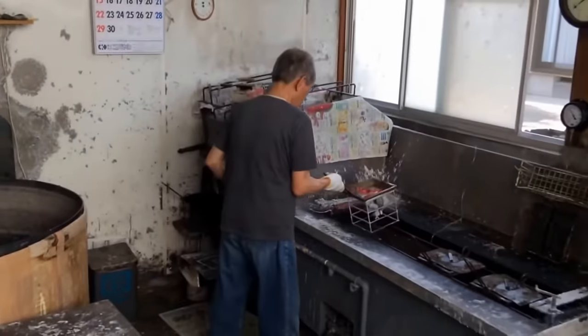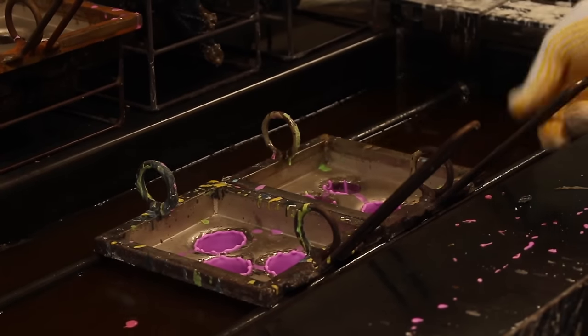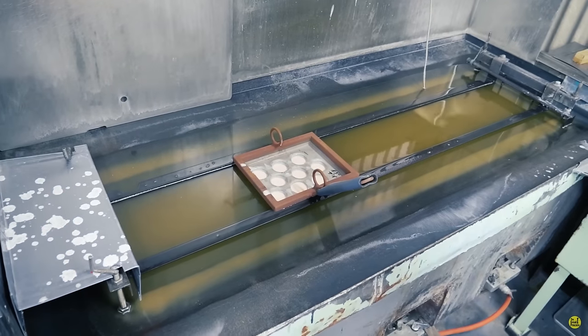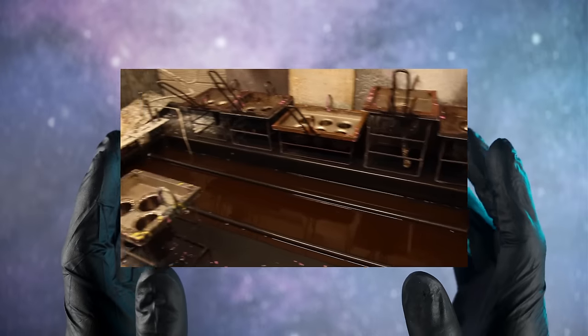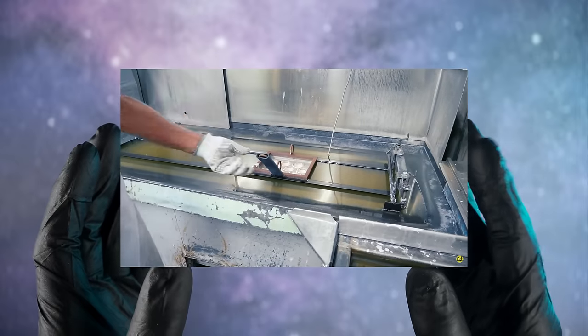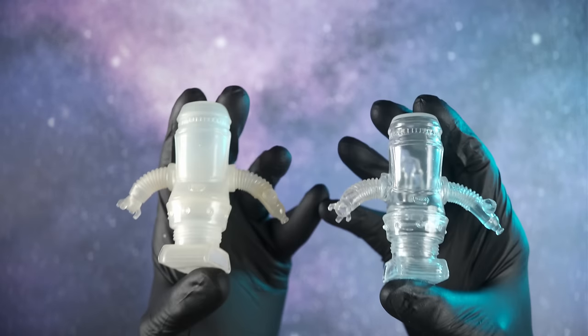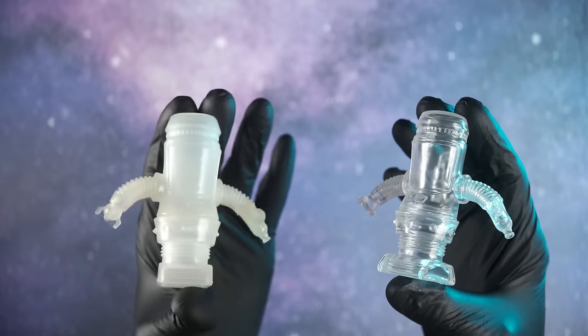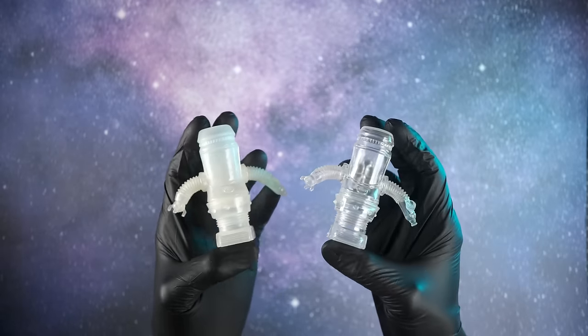And now they take the vinyl-filled mold and set it down into a hot chemical bath. This is pretty interesting right here. This chemical bath reacts with the outside of the metal mold, curing the layer of vinyl inside the mold that's touching the metal. Now, what's actually in these vats is a bit of a mystery. Some people use oil that's heated to around 180 degrees. Some people use a mixture that involves, I have heard, toluene. It's considered trade secrets to some people. But I have been told that it does make a difference. If you're doing clear, you probably don't want to use oil. But if you're not doing clear, oil bath is okay. But it does make a difference. I have been educated on that.